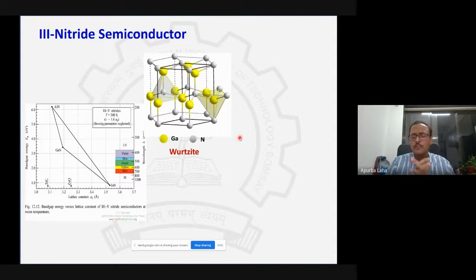Another interesting and unique property of gallium nitride, or III-Nitride material, is that if you mix the three different elements I'm talking about, indium, gallium, and aluminum, with the nitrogen, you can cover the entire visible spectrum, and all the way reach deep UV, as high as 250, 220 nanometers, for example. That is given by the figure on the left. Aluminum nitride, group 3 aluminum and nitrogen, has a band gap of 6.2 electron volt, which would give you light at a wavelength of 210 nanometers.